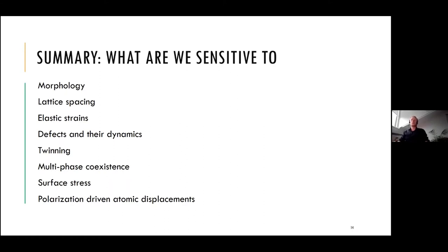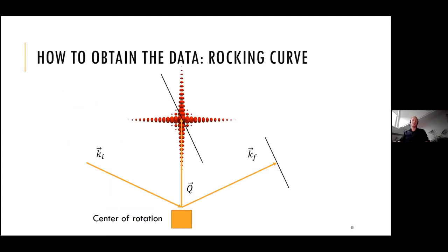Moving forward, so that's all fine. We can get all this nice information, but how do we actually obtain the data? If we continue the discussion in terms of k-vectors, how to record the full three-dimensional information around the Bragg points in the actual experiment. In case of the forward scattering, you just rotate your sample and you get slices through the center of the diffraction pattern, and then you can stack them in 3D. But in the case of Bragg CDI, Bragg coherent diffractive imaging, you have to place your object into the center of rotation of the device, which can reliably record the scattering. And here you see the incident beam KI and scattering beam KF, and you record it at the detector.